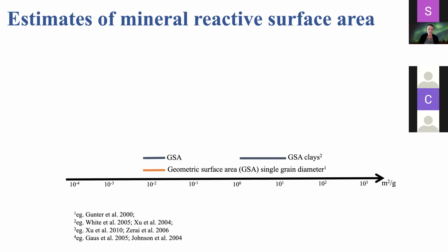However, this is also an oversimplification because we know that real mineral surfaces are not perfectly smooth. They have some amount of surface roughness. So we can account for this by applying a roughness factor. This is typically a value of 10. This rough surface area can also be measured in the laboratory with a BET analysis.